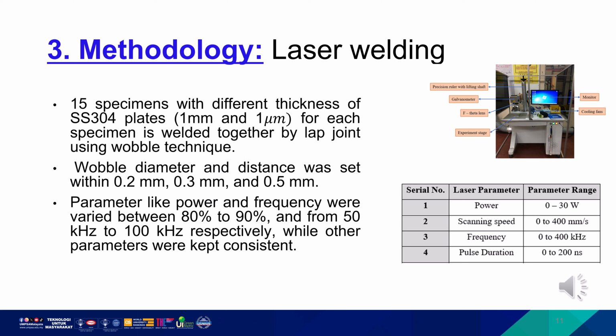We laser welded SS304 samples, 1 mm and 1 micrometer, using the wobbling technique, and testing of the different parameters such as wobbling diameter, power and frequency was carried out while keeping other parameters constant. Here is the range of parameters that were used in the experiment.